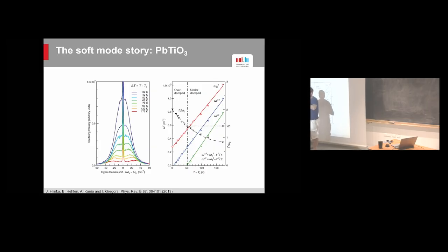Below TC, you're blind. You can't see anything. So what you see here is a very clear soft mode behavior in the sense that you have a bump here that goes quietly to 0, right? It's definitely not as nice and sharp as you would get in proper Raman.